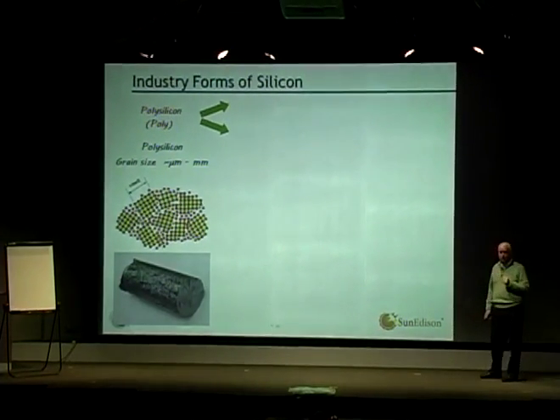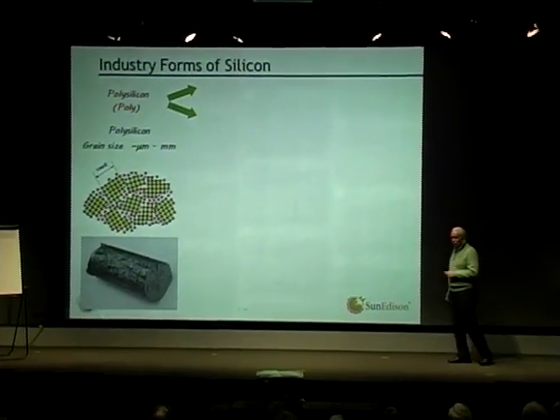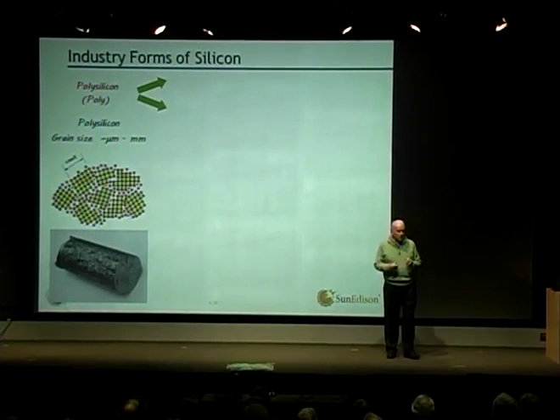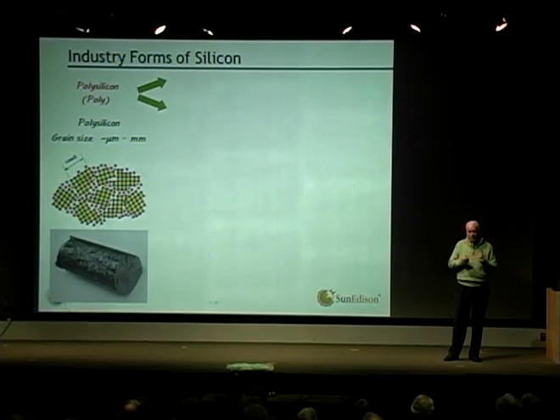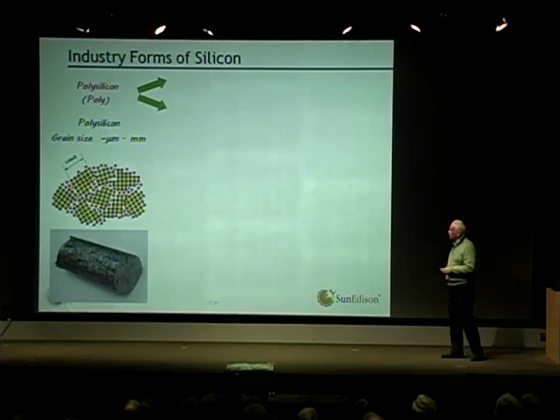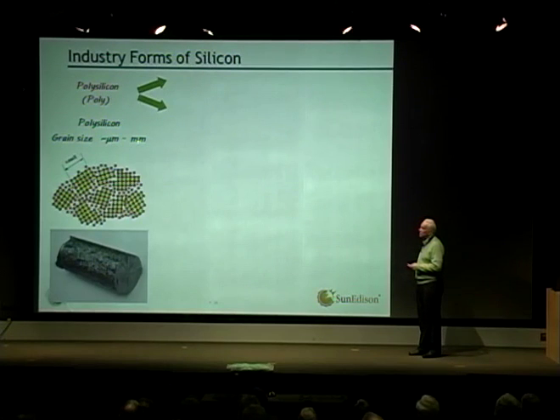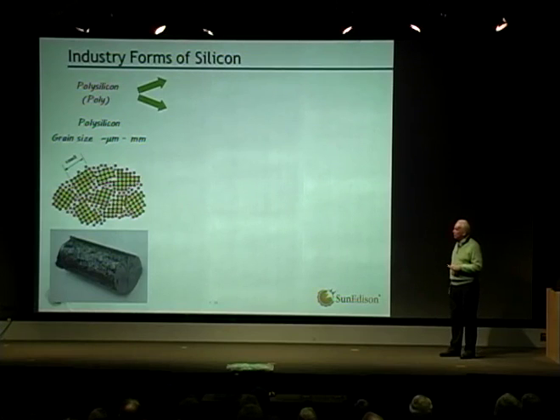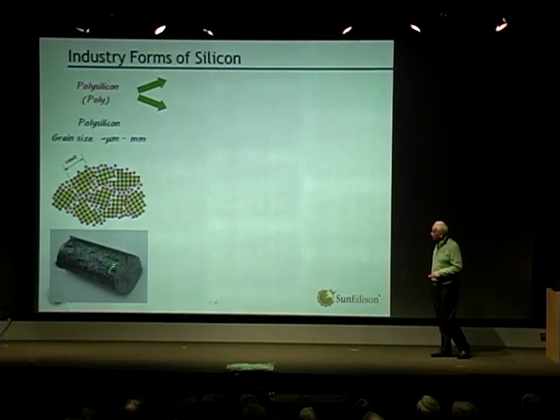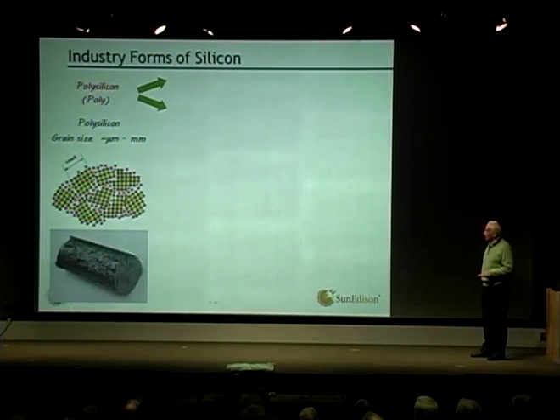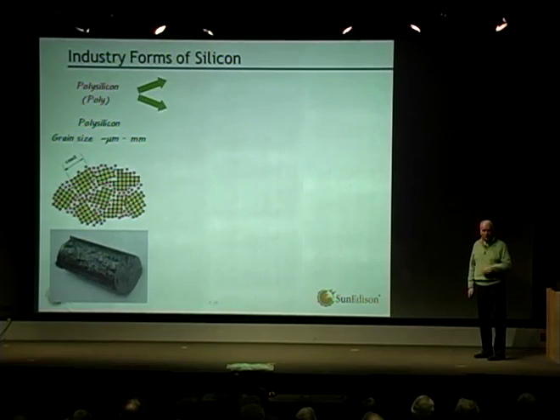I come up with this term polysilicon to differentiate some of the terms that we use. Most metals, you pick up a piece of metal, it's polycrystalline. That means it has tiny, tiny crystallites inside it in all different orientations, and lots of defects. But the crystallite sizes, in polysilicon at least, are on the order of microns to at most about a millimeter. If you look under a microscope, you'd find all these very tiny crystals, lots of them joined together at different angles, as represented here. And there's a picture of one. When you pick something like that up, you can tell that it's polycrystalline because you can see all the little grains in it. If you take a steel bar and cut it and look at it, you should be able to see grains on the end of it, particularly if you were to polish the end and then etch it slightly. You would see the grains of steel, or copper or brass, any metal really would show you that same characteristic.